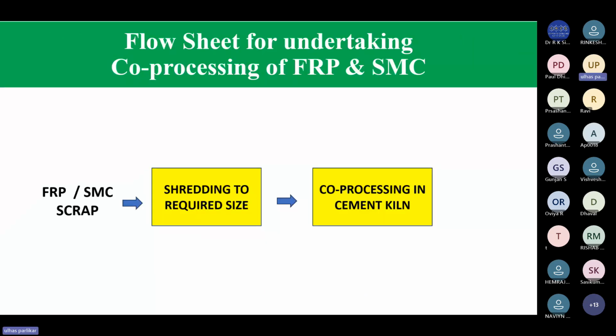What is required for the FRP and SMCs to get utilized in the cement kiln? The cement kiln requires a certain specific size, that is the limiting size. It has to be less than that, and only then can it be utilized. So this needs to be shredded. Like I said, Suzlon in Pondicherry had set up a shredder, and the material that was getting generated as scrap was sent through this shredder. The size was brought down to less than 25 millimeter. That was the requirement for the Madukarai plant.